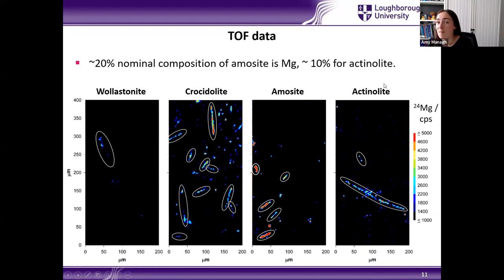So if we have a look at magnesium now, 20% of the nominal composition of amosite is magnesium. So we see very strong signals for the fibers in our amosite image. Magnesium is also present in actinolite as well. So as expected, we see strong signal here. It's not expected to be present in wollastonite. We don't see much magnesium there.